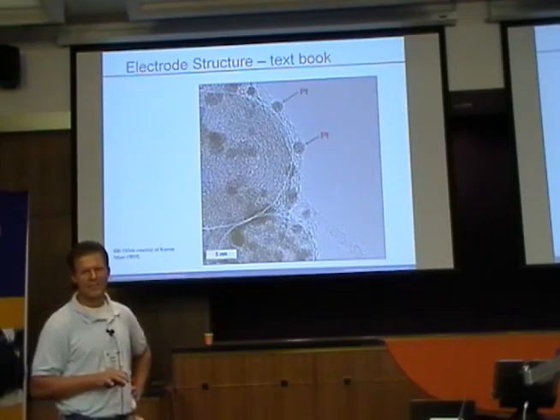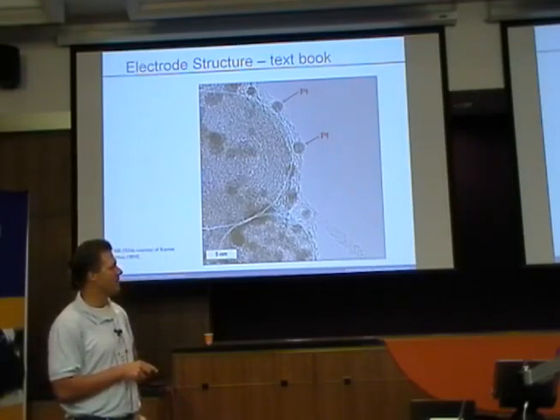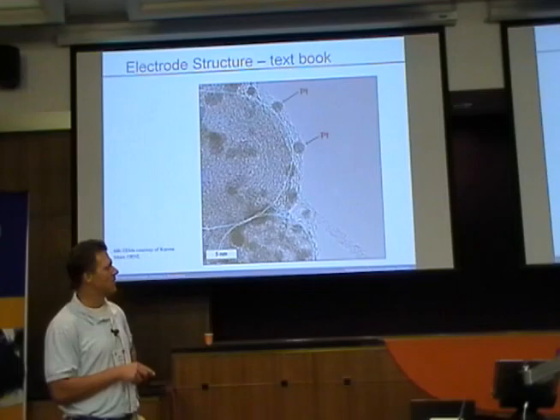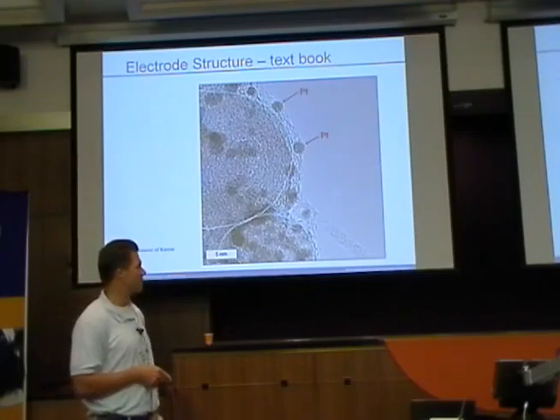There's a lot of catalysis applications similar to this where you wouldn't need an ionomer because you'd be doing it in a liquid solution. And you could put acid in the liquid solution. But in a fuel cell, you have the most complicated version of this because you have to have this thin ionomer skin because you need it for the ion conduction. But if it gets too thick, what happens is the reactants can't get in, and the products are slow getting out, so you have a lot of mass transfer problems.